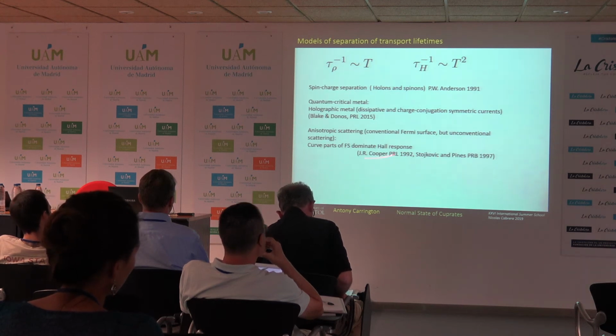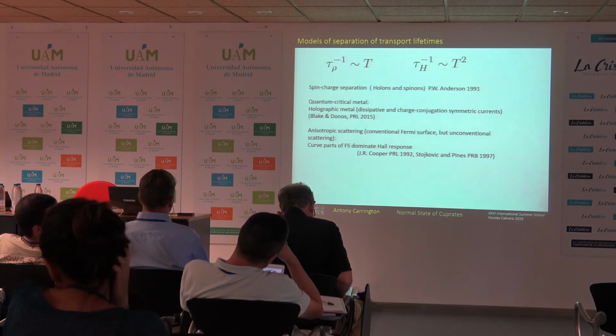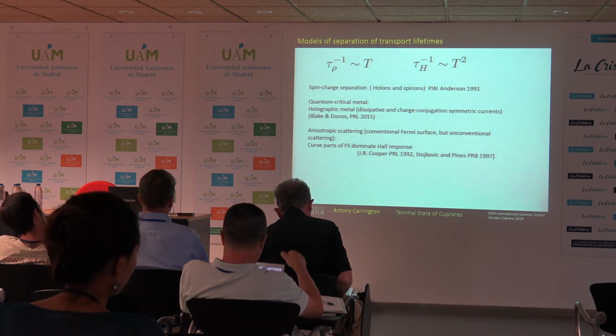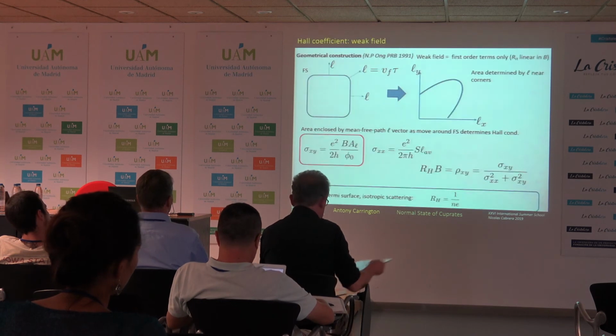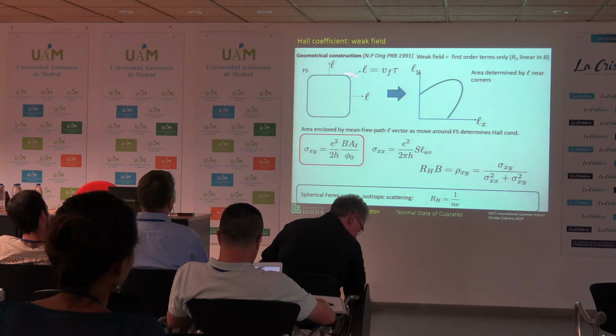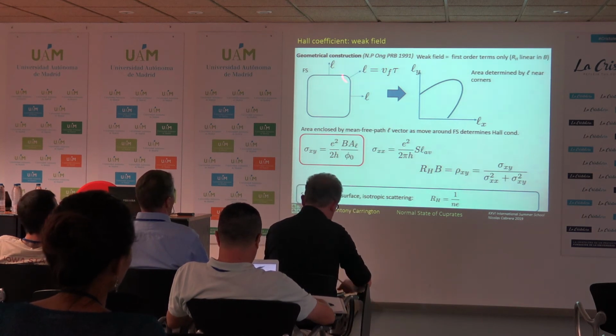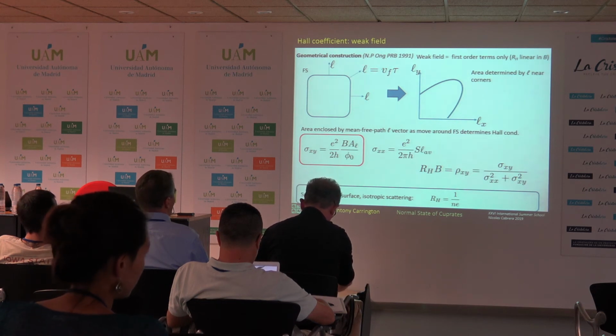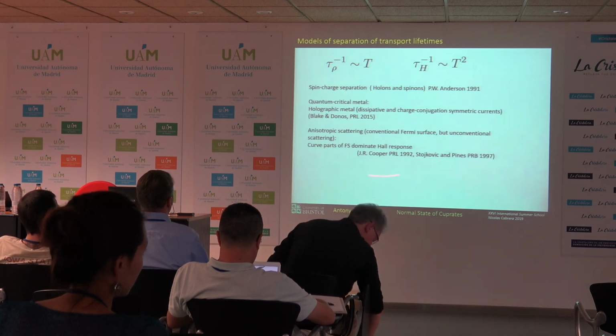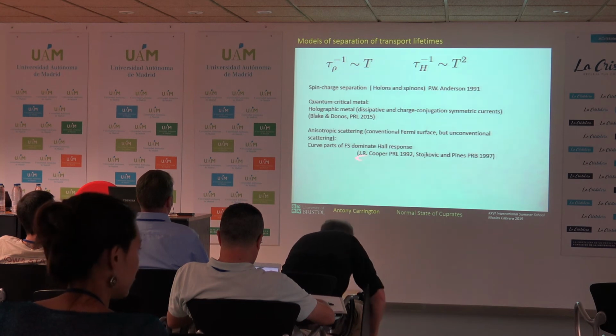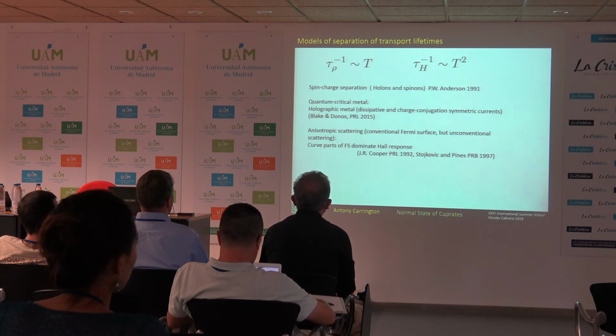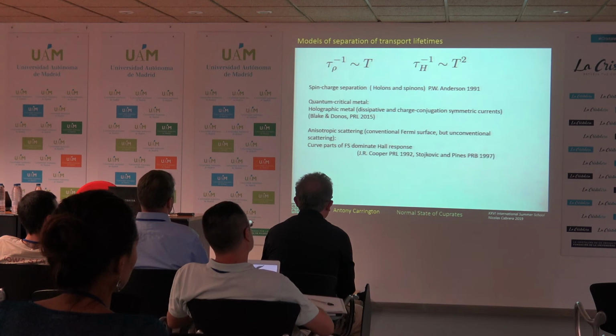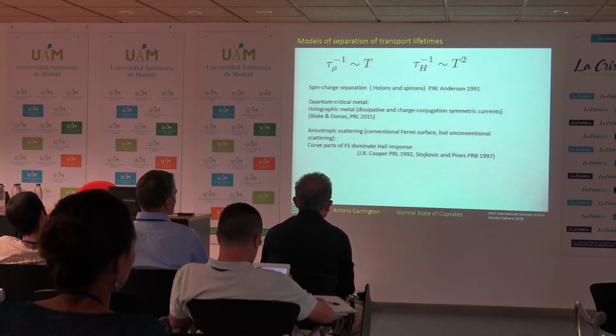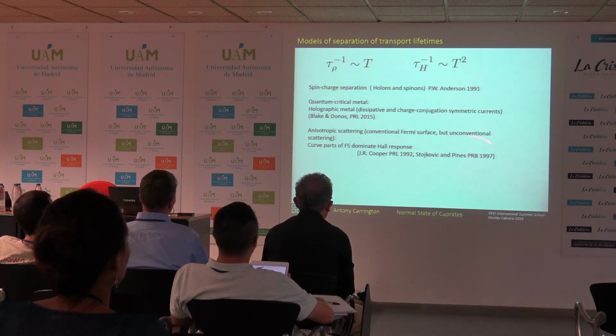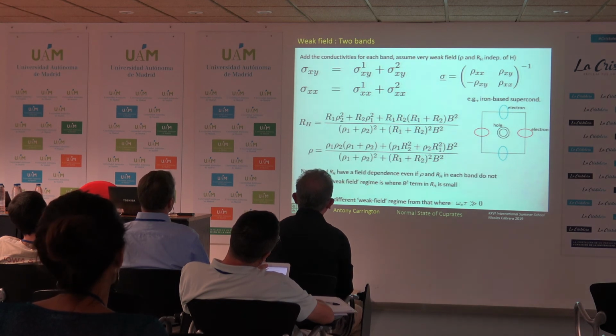On a more vanilla basis, based on this sort of picture, you can also, to some extent, explain what's going on just using anisotropic scattering. So you've basically got a Fermi surface, and then you've got a scattering rate which varies around the Fermi surface, and this fact that the Hall coefficient is dominated by the bits on the corner, you can exploit by making the scattering rate on the corner go like T squared, and the scattering rate on the flat bits go like T. Now, does this work? This was originally, as far as I'm aware, proposed by John Cooper back in the early 90s, and it kind of works, but only if you really tweak the parameters. So you can get it to work, but it's very unlikely, in my view, that it's the definitive explanation, because it only works for very particular parameter sets. Okay, we'll get into that.